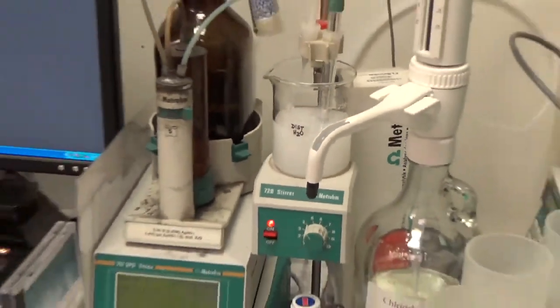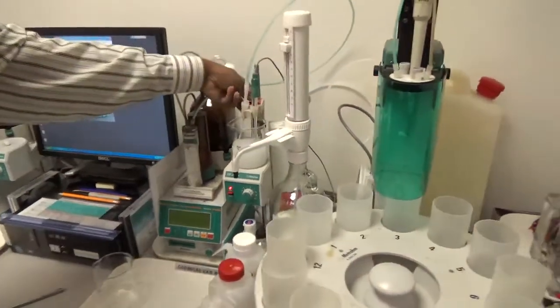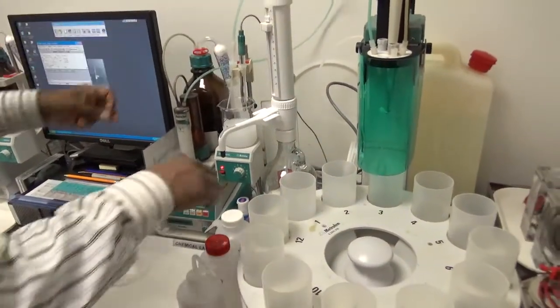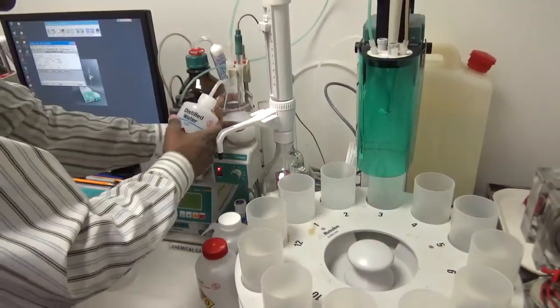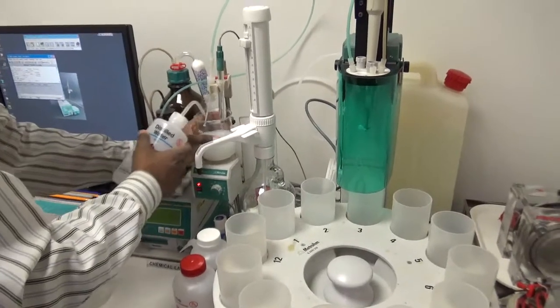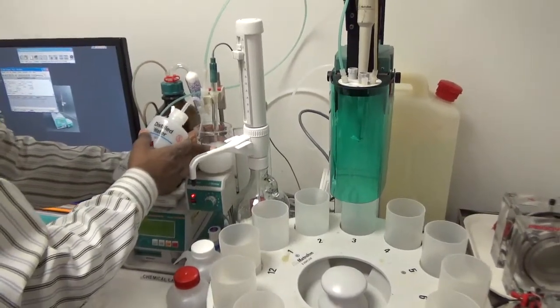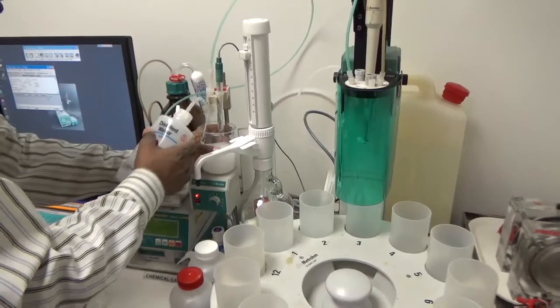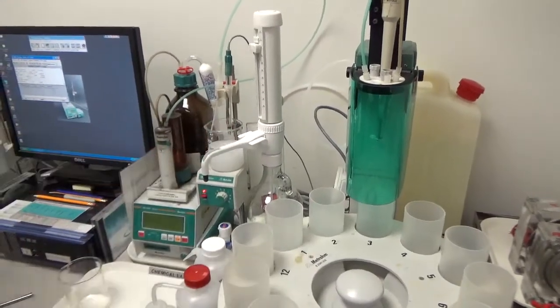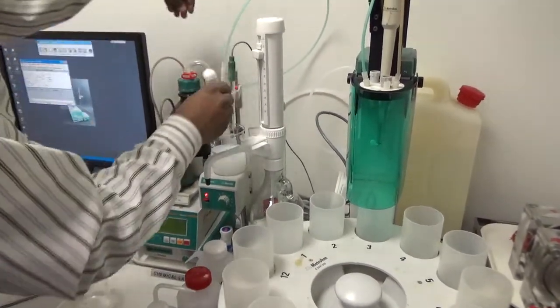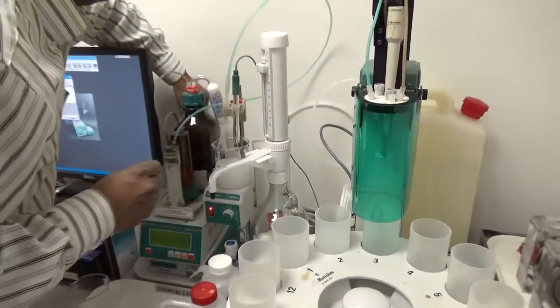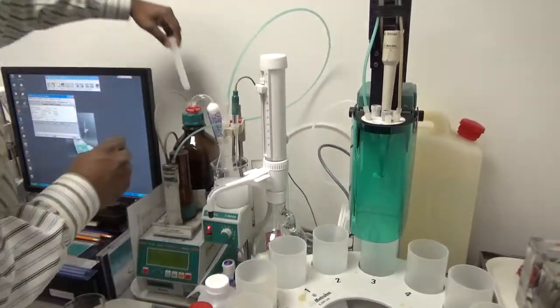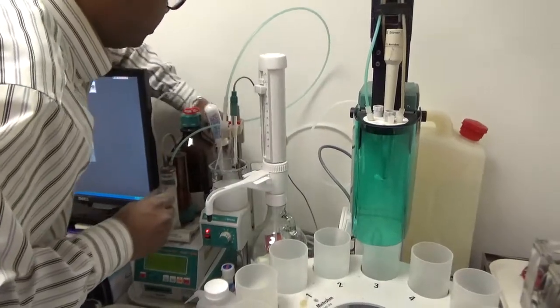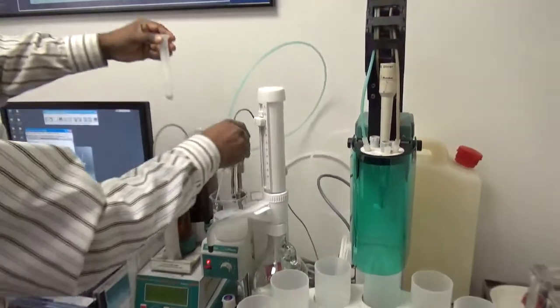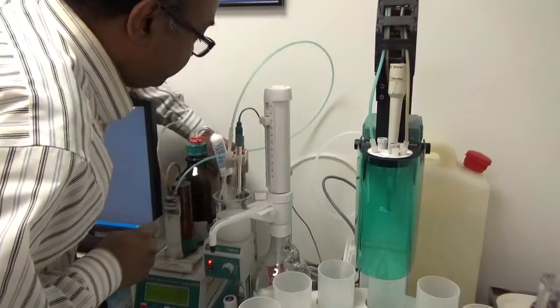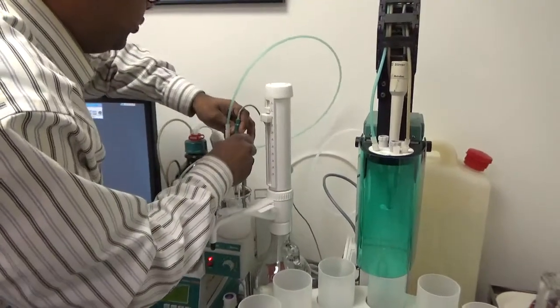So once the titration is done, I usually move the electrode and the burette out, clean it with distilled water. Since I don't have an automated cleaning here, you clean with the distilled water. Then we take the electrode out and we put the electrode in a potassium chloride solution, storage solution. Always make sure there is storage solution.